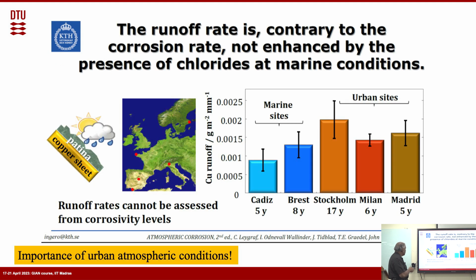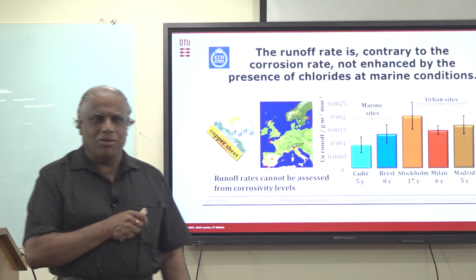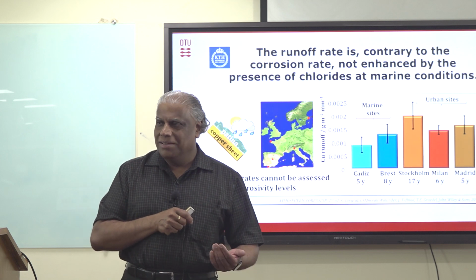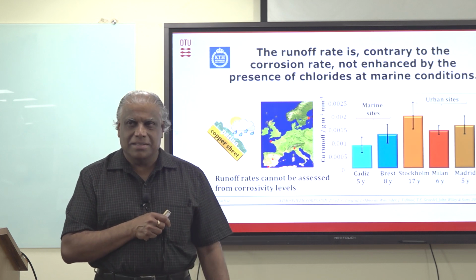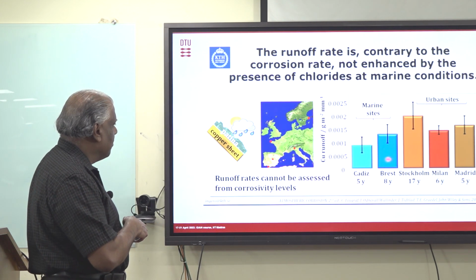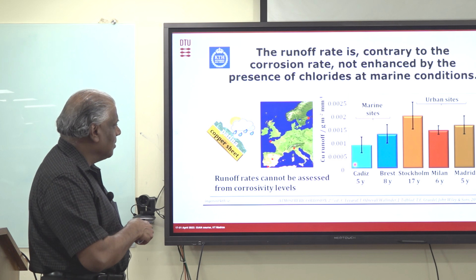And so one of the results which they have, and they did studies at different places related to this copper runoff from the patina. What they found was, you can see here, these are different cities and places in Europe. If you take the marine sites and urban sites, you can see the marine site is actually lower, right? The runoff rate is lower in the marine site, because usually we expect the other way. The marine site has a lot of chloride conditions, and we expect that marine sites will give much more runoff. But here it is opposite.